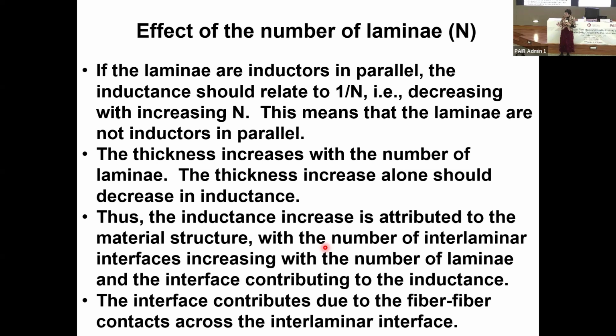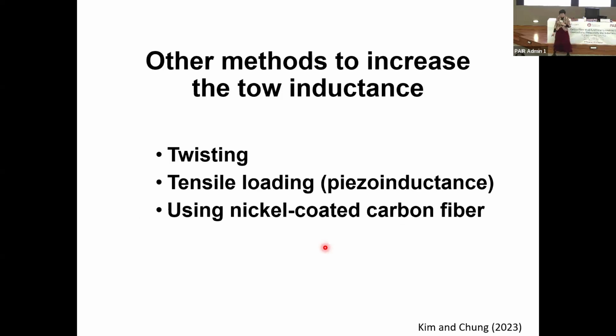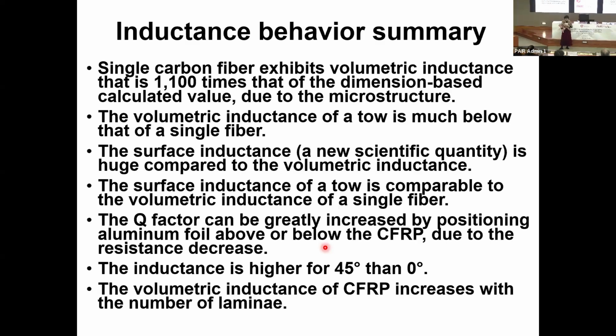And the interface contributes due to the fiber-fiber contacts across the interlaminar interface. There are other methods to increase the tow inductance. I don't have time to cover that. Twisting the fiber tow, tensile loading, that is piezo inductance. Also using nickel-coated carbon fiber as opposed to uncoated carbon fiber. All these help to increase the tow inductance.